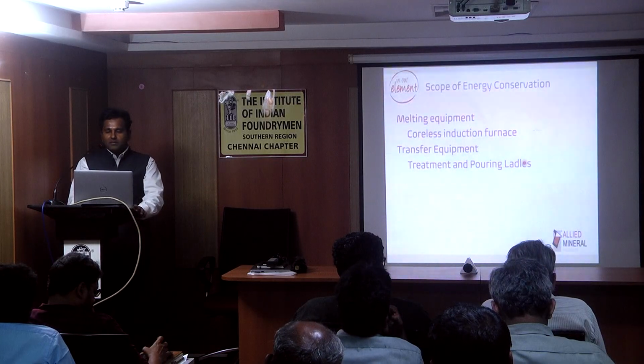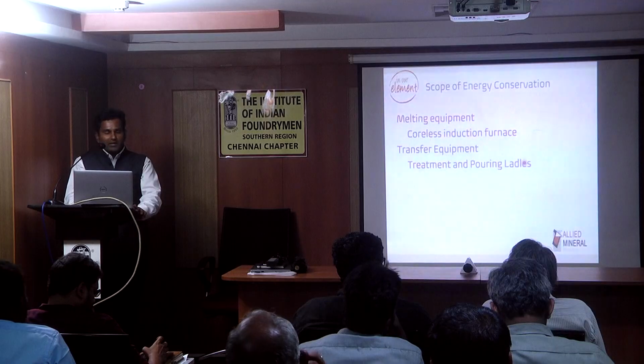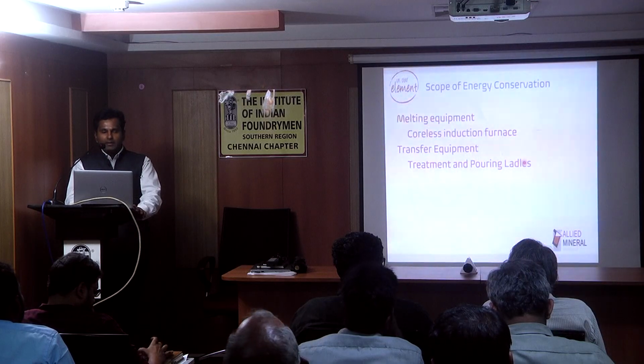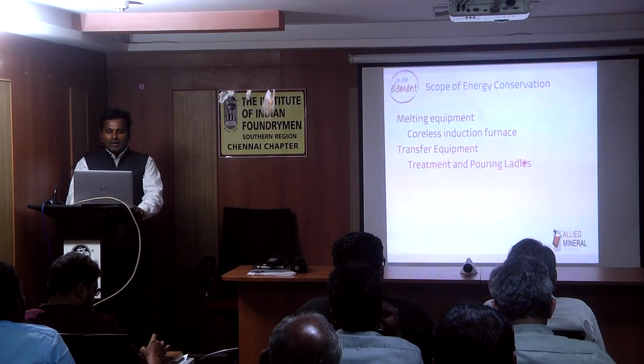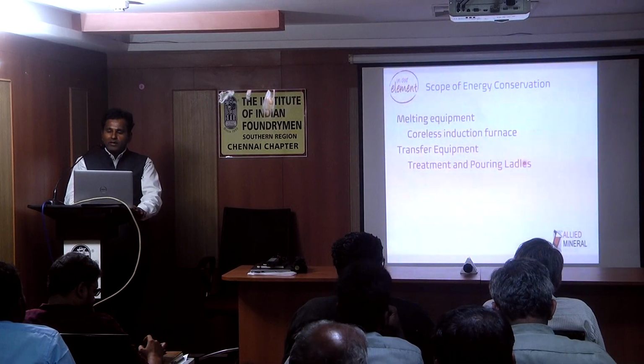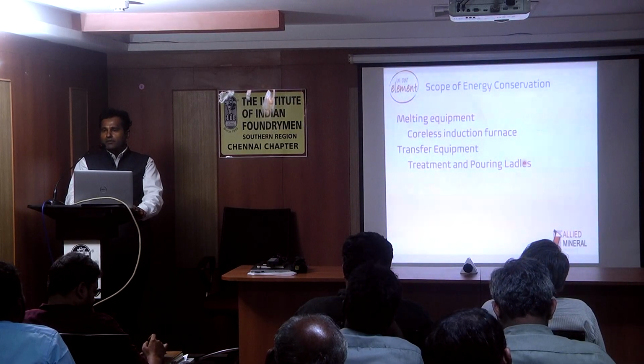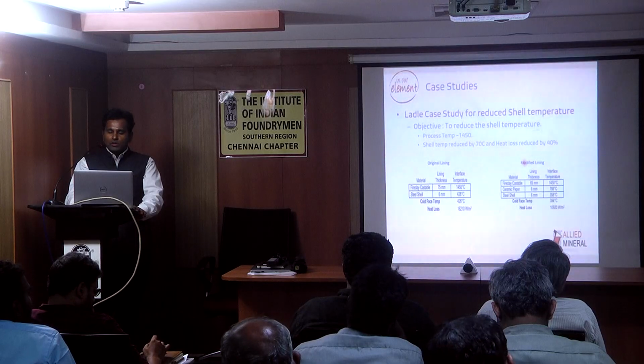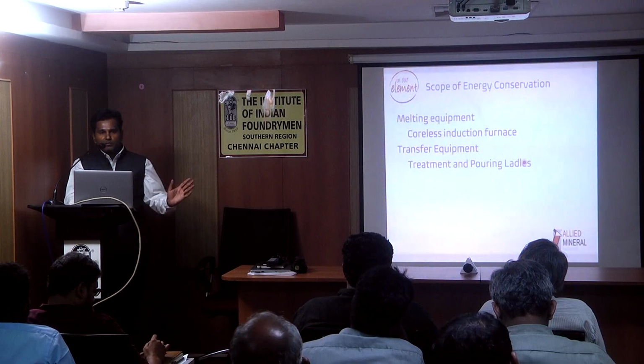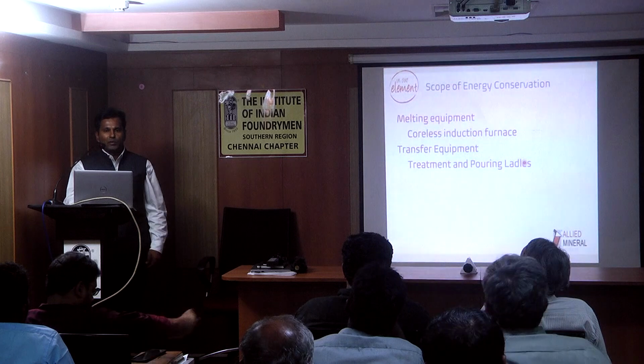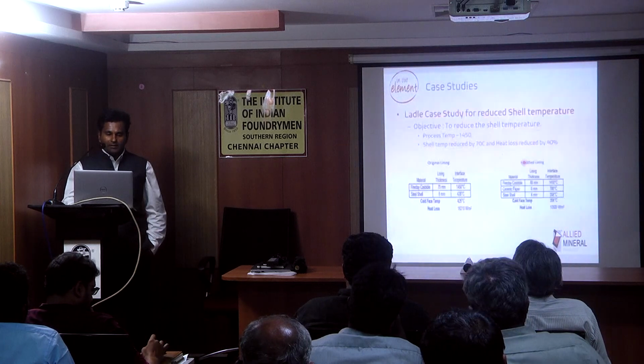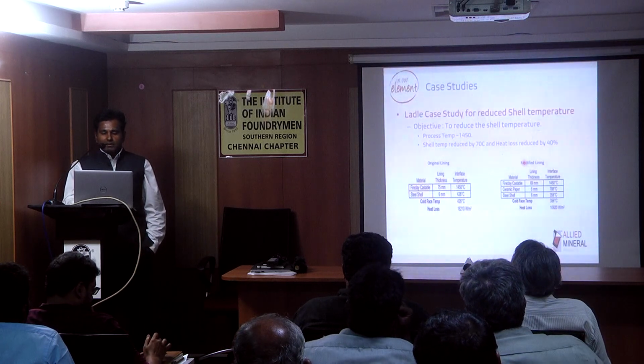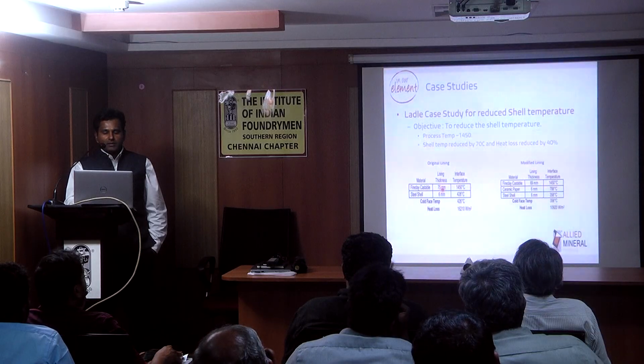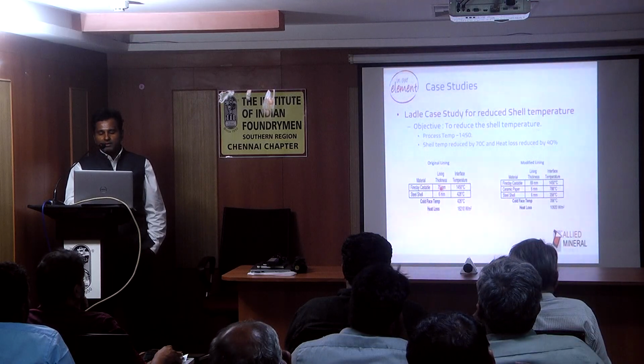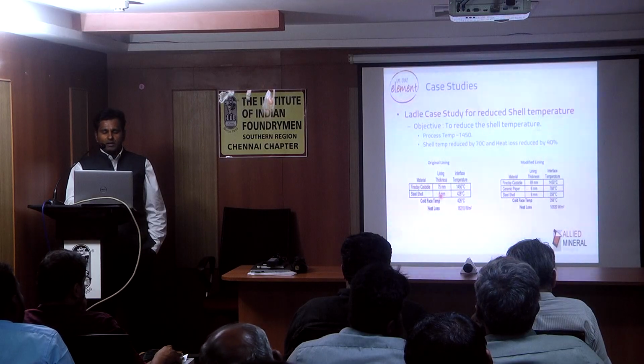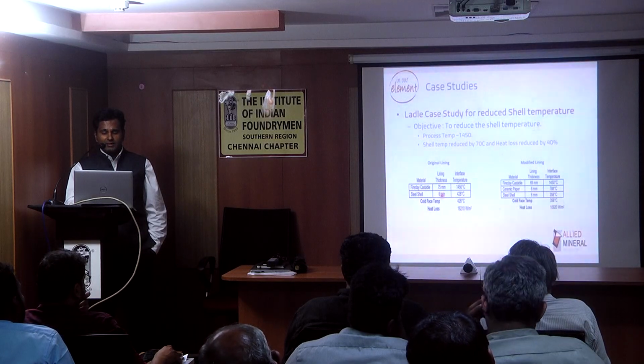Regarding the scope of energy conservation in melting equipment, coreless induction has a major scope, which is already briefed by Mr. Anand sir. And transfer equipment, treatment and pouring ladles are also an effective way of saving energy. I have 3-4 real-life case studies where you can get an idea how to save energy. In one ladle, the lining thickness is 75 mm of fire clay based castable, directly lined onto the steel shell.